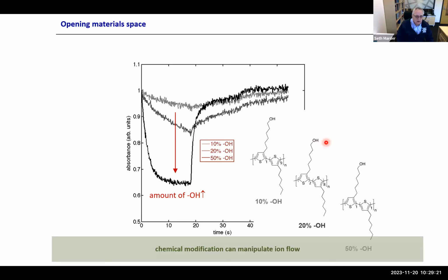Can you just explain the experiment a little more? Okay, yeah, I'm sorry. It's really photoelectrochemical spectroscopy. So you have a film, you measure the absorbance, and the film is exposed to electrolyte, and you apply a voltage, a bias across the system. And the bias is electrophoretic bias or redox? It's redox, yes. And I apologize, I should have had the graph. It's redox. So you apply the bias, you get the ions in, and therefore you either oxidize or reduce the backbone. I see. Does that make sense?